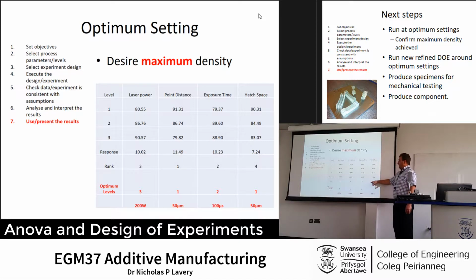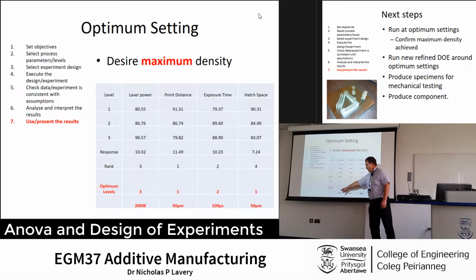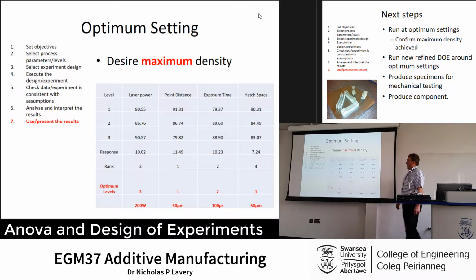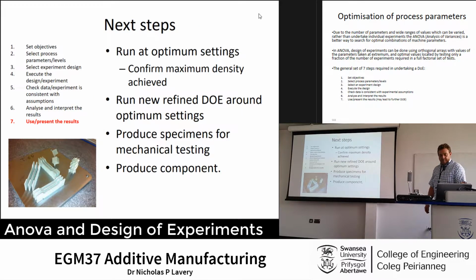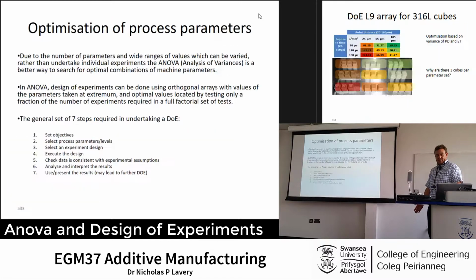Now, that ranking there allows us then to choose what the optimal settings would be within the ranges, so we can then play in that scope. So here, that would give us a 50 micron point distance, give us the highest density, and then we can also pick out the other values based upon those optimal values. We might want to then refine around that and do an experiment with a smaller range of the parameter levels that you choose. And that's it.